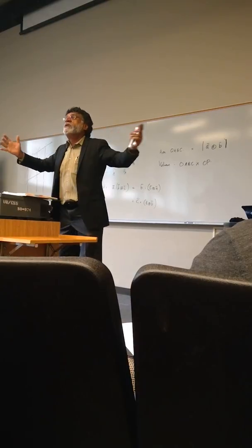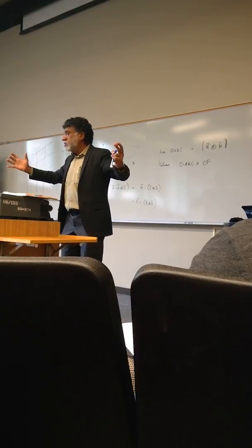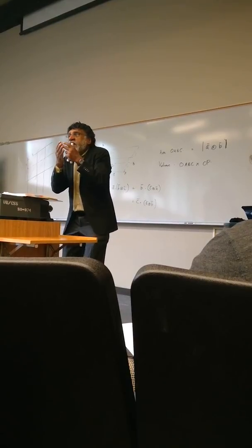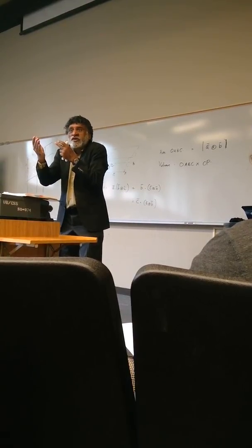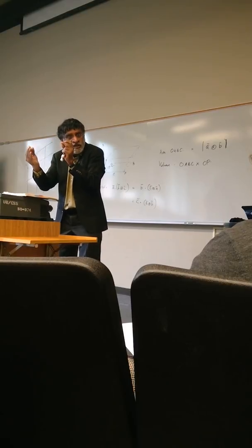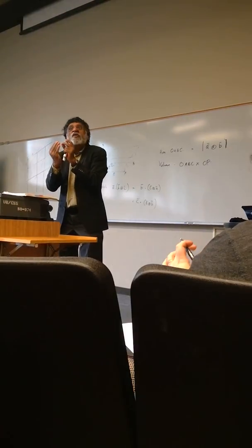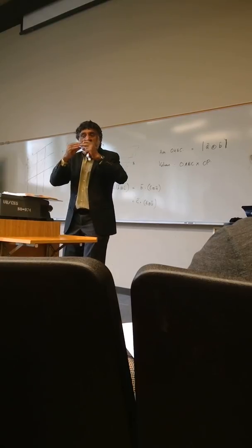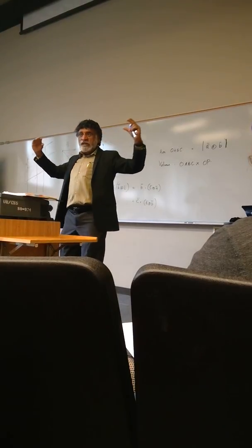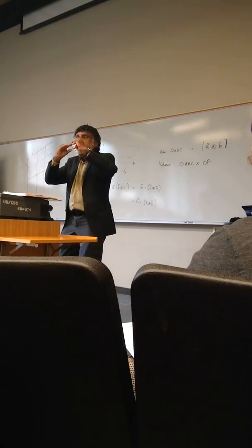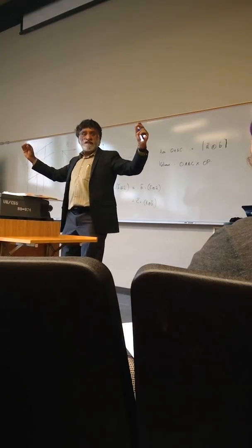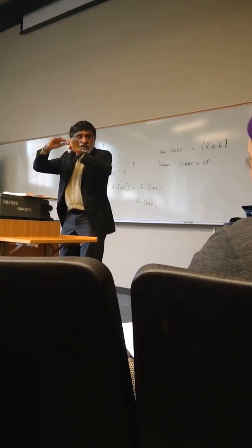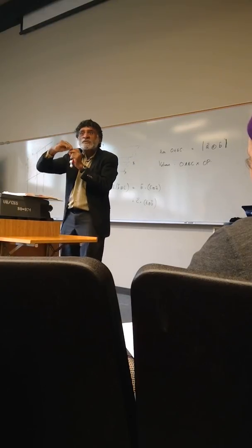You don't have so many lattice points. If you get to a small round object, you have maybe 100 lattice points, so there are only 100 lattice points. This will become quite finite in size. If you have a long precipitate like this, in this dimension you may have a zero-dimensional object, but in this dimension where the precipitate is thin, you will have an extended object.